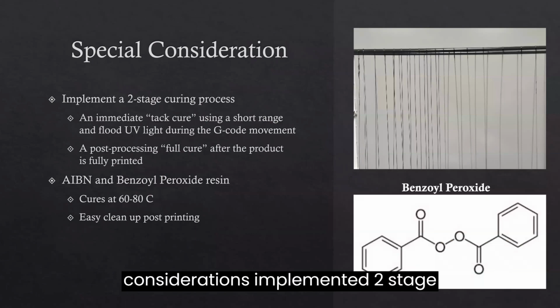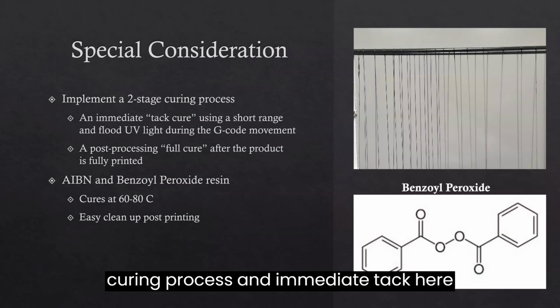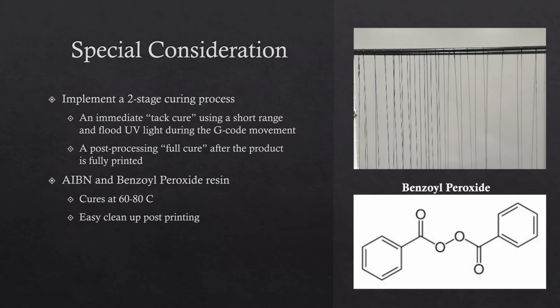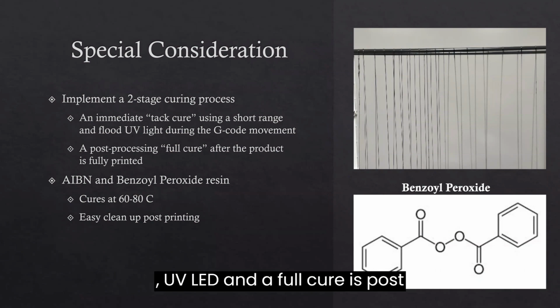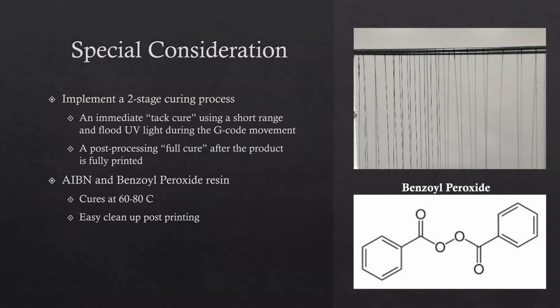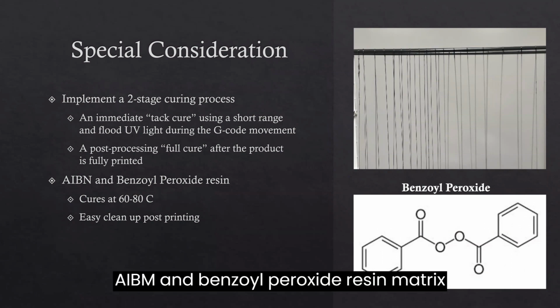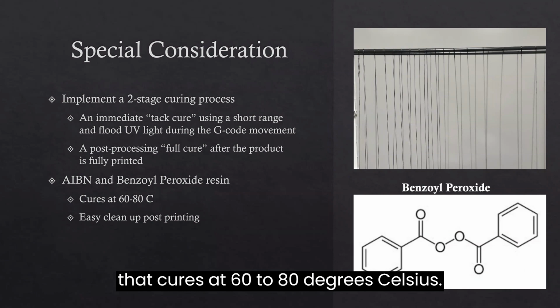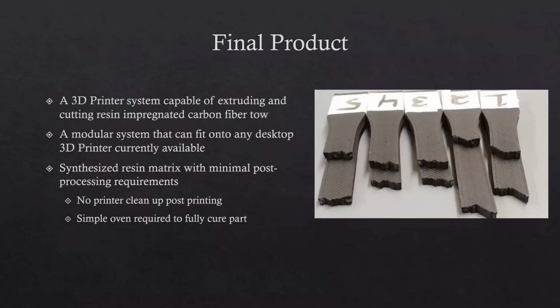So for our special considerations, we implement a 2-stage curing process. An immediate tack cure is used on short range flood UV LEDs, and a full cure is post-process using an AIBN and benzoyl peroxide resin matrix that cures at 60 to 80 degrees Celsius. This is great because it's easy to clean up post-printing.